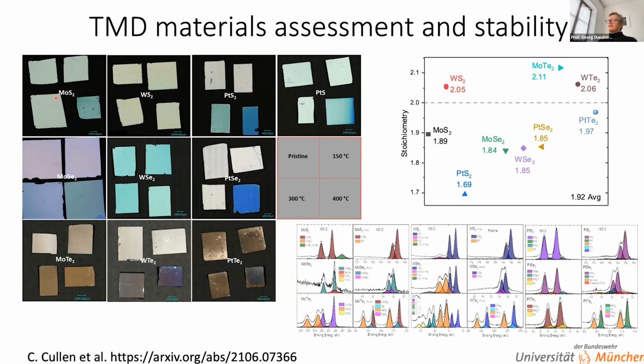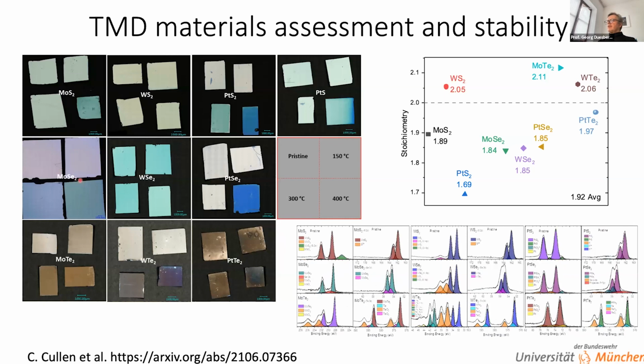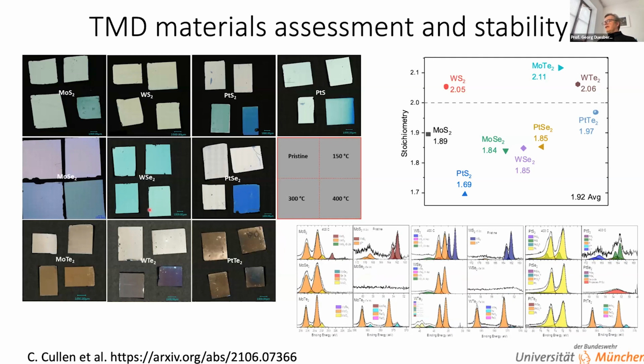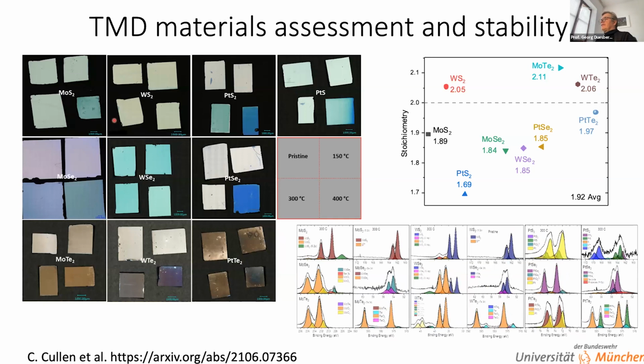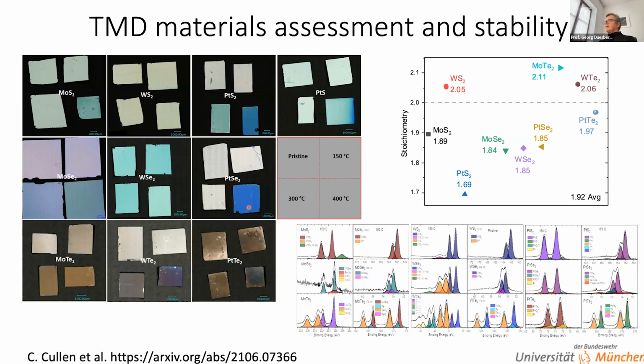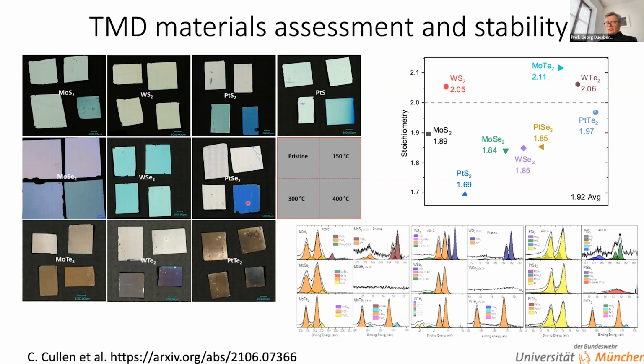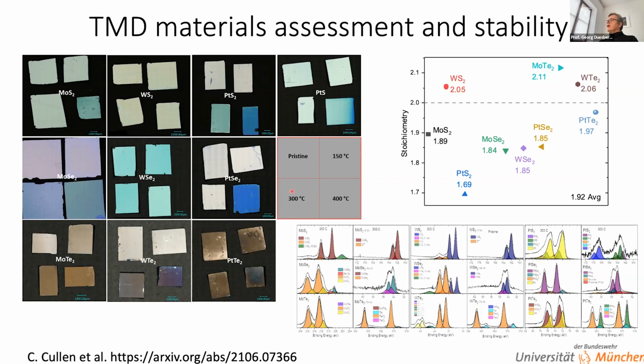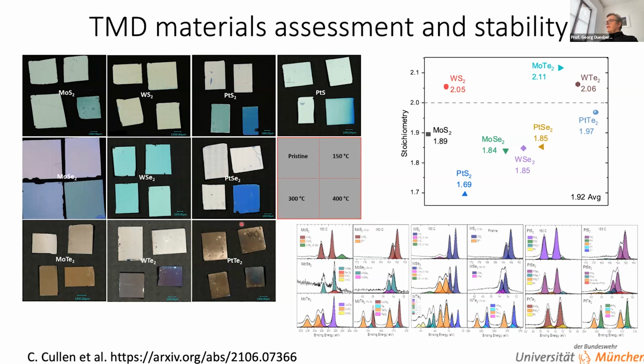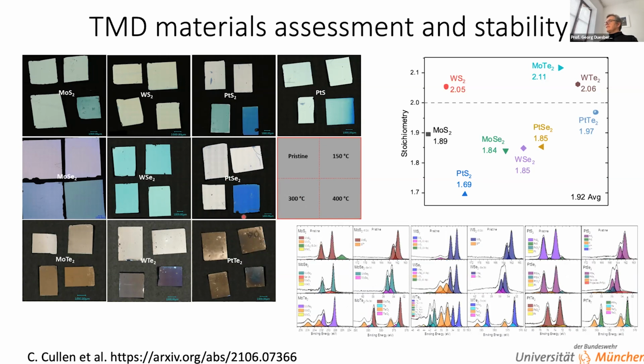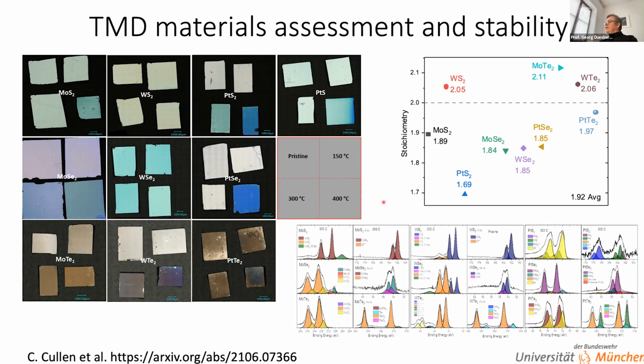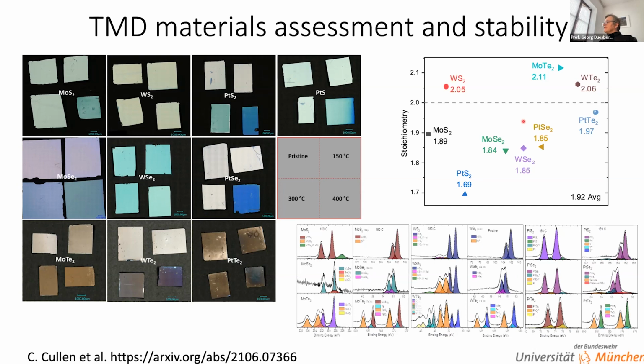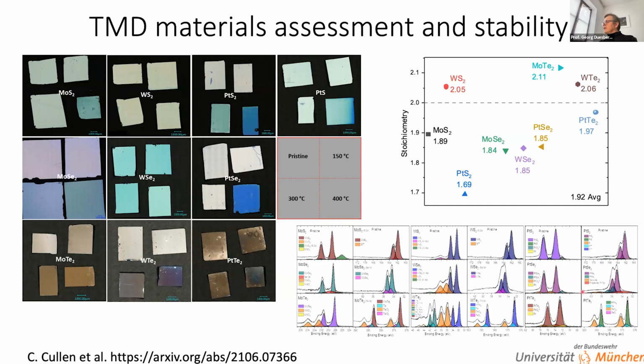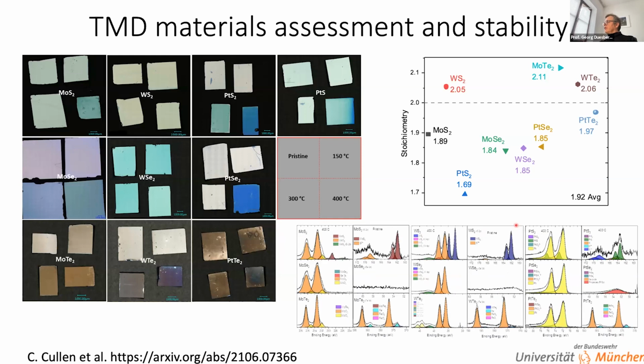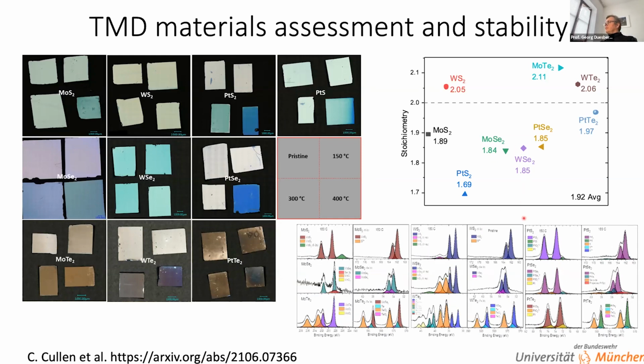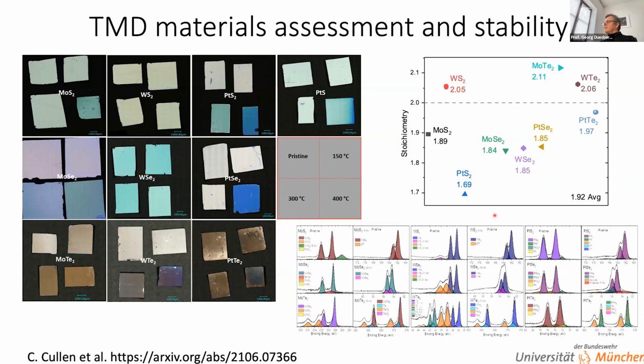The usual suspects, MoS2, WS2, Mo and tungsten selenides, but we also managed to make the tellurides of those two. But in particular, we had focused on platinum compounds, where platinum diselenide turned out to be a very nice material to make, and which I will further talk about, but some others are possible. Here is some XPS structure which is available on all those materials, and their stoichiometry according to XPS and Raman studies.